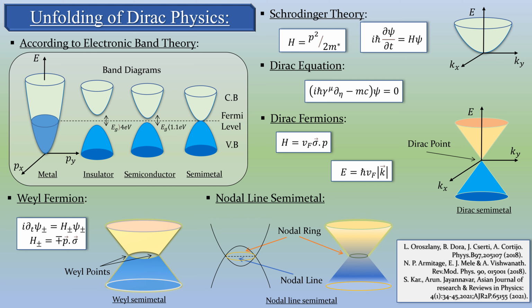To work with linear crossing, we have to use the relativistic Dirac equation rather than the Schrodinger equation. Here is a continuum model that resembles a massless Dirac Hamiltonian. Typically for graphene, it produces the so-called Dirac points where the conduction band and valence band touch, the dispersion being linear at that point. In 3 dimensions, we have the massless Dirac equation. Thus, fermions propagate parallel or anti-parallel to their spin, which defines their chirality. Those are the Weyl semimetals.